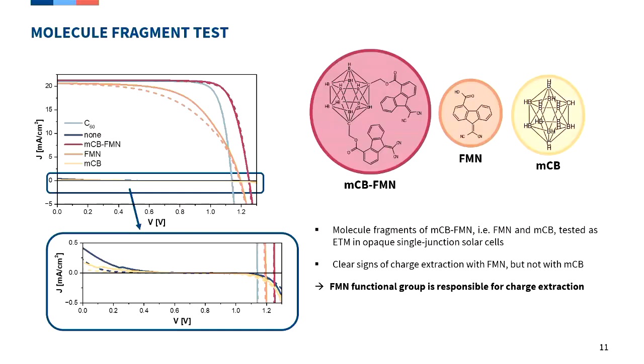We also did a single component analysis, making solar cells with only the single components. The carborane alone doesn't show any photocurrent at all - it's just a flat line. This molecule works by itself, interesting, but the JV curve - the fill factor and the VOC - are slightly reduced. So it's working, but not giving the performance you'd need. You need the combination of both.